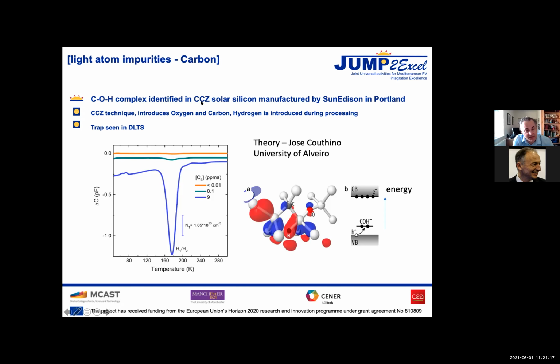Oxygen's in there anyway, because I've already said it comes in from the crucible, and in some ways it's desirable because it hardens the silicon for sawing. But then when you make the silicon cell, you push hydrogen in. And we found, and they came to us because they were having a problem in the lifetime of the minority carriers, which I'll come to in a moment, which was reducing the efficiency of the cells they made, that there is a complex of oxygen, carbon, and hydrogen formed under certain conditions. This is actually minority carrier transient spectroscopy, but it's a form of DLTS. We see an emission peak here at a particular temperature, and we have some friends over in the University of Aveiro in Portugal who do calculations, and they were able to identify this as a complex of carbon, oxygen, and hydrogen.